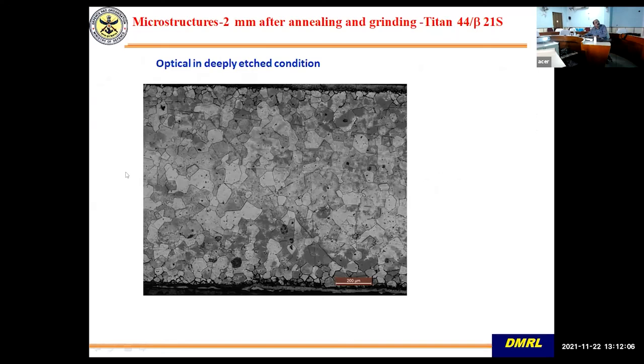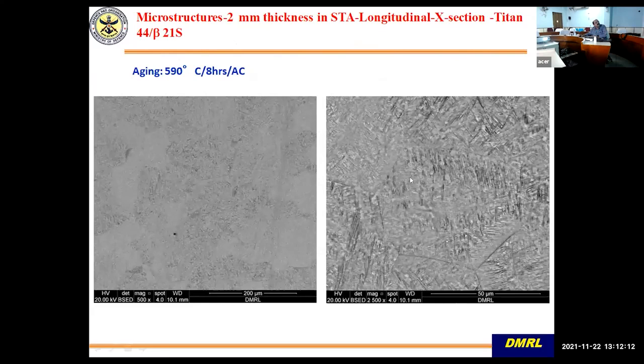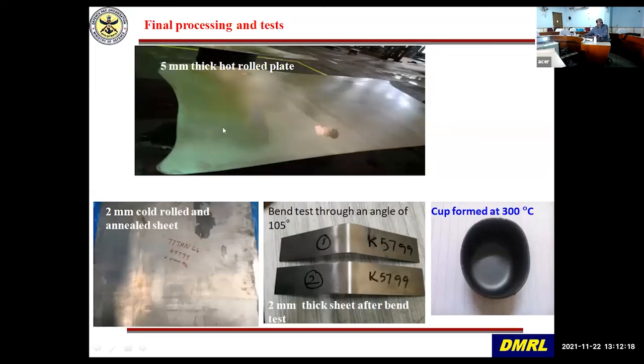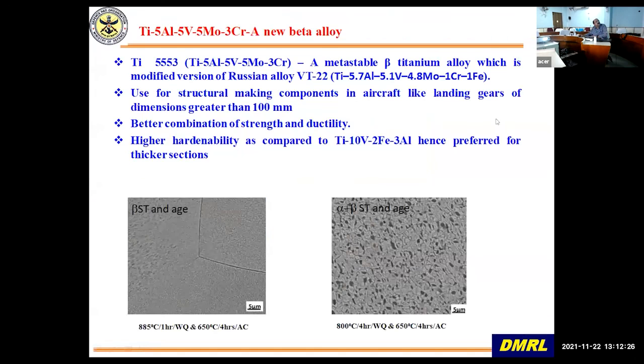You can see big beta grains which are there. This is the condition in which it is to be supplied. Then when you age, you get very fine precipitation, big beta grain, very fine precipitation of alpha. That gives strength. Okay, so sheets are made, bend test, cup test, etc. Sheet applications were done to check the material, and it turned out.